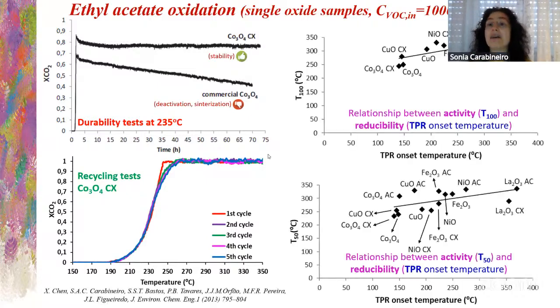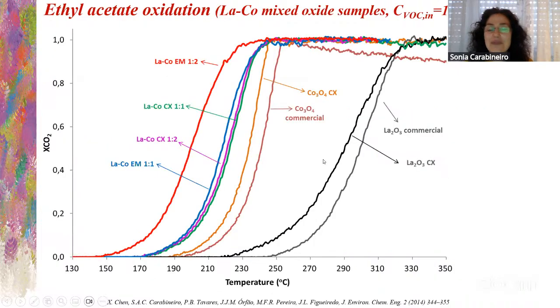Here we have a relationship between the activity, the temperature at 100% conversion, and the reducibility, so the onset temperature of the TPR. So we see here more or less this relationship. Here between the T50 and the TPR onset temperature. So we were trying to find relationships between the temperature and the onset temperature of the TPR, to find if they were correlated.